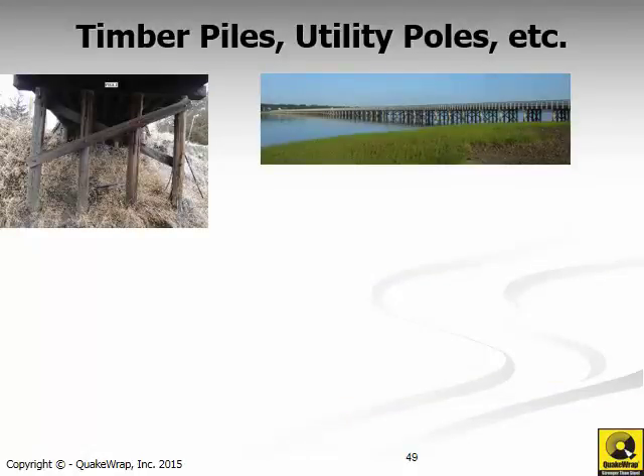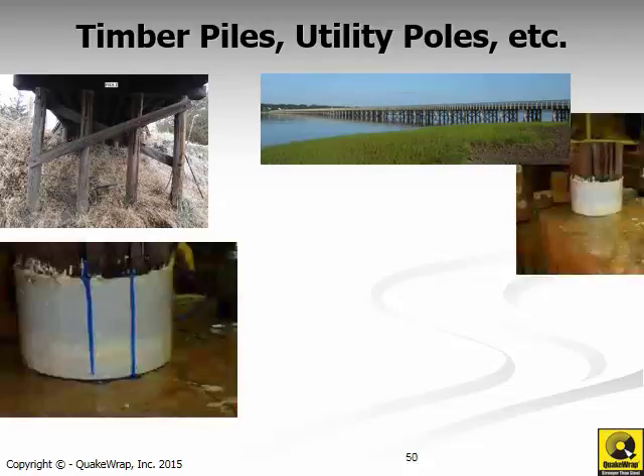We can also repair timber piles with PileMedic, the systems that we have developed. In one of our earlier demonstrations, we took a piece of a pile and wrapped it with a PileMedic jacket as shown here. Instead of putting grout in there, we prefer to fill the annular space with a low viscosity resin. We do not need to keep a large annular space. In fact, it is preferred to keep it very small to keep the cost down. But that low viscosity resin will find its way and penetrate through all the voids and cracks of the wood and provide a very solid and strong structural element.